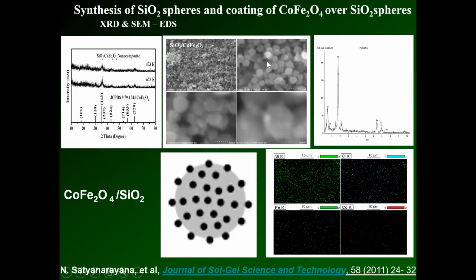So then you can see this SiO2 coated. You can see white dots. With magnification, you can see that over this SiO2 you can see these dots. When you analyze these dots, they are actually cobalt ferrite.